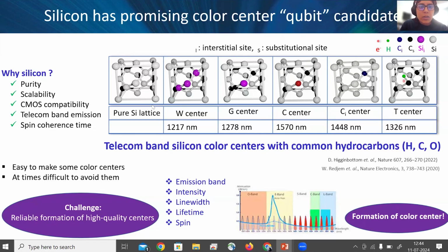Now here on top, these are different color centers that you can have in silicon. For example, the W center forms when you kick out 3 silicon atoms from their lattice positions. So now they are sitting at interstitial sites in the lattice. And if you have 3 of these silicon atoms in the near vicinity of one another, they form this color center called a W center. And if you excite them with some laser, you can have the emission at about 1217 nanometers.